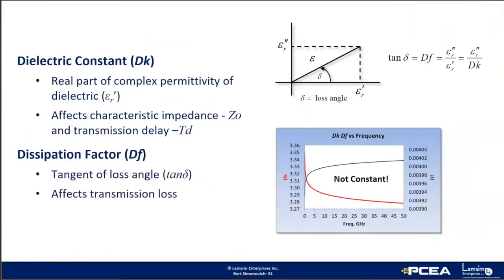The dielectric constant is the real part of the complex permittivity. It affects the characteristic impedance of the transmission line and the delay of the signal. The dissipation factor, or tan delta, is the tangent of the loss angle, and it affects the transmission loss of the signal. And as you can see by this graph, Dk and Df are far from being constant over frequency.